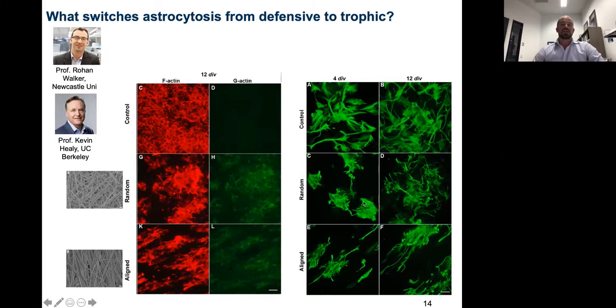What we found is that when we offered these three-dimensional architectures, these fibrous morphologies, which are electrospun polylactic acid fibers, the same as the degradable stitches you might get from a dentist that you don't have to remove, there's a much lower cytoplasmic volume, and these cells have a very different morphology to the inflamed ones up here. So we managed to maintain them in vitro, for the first time, in a state that was not inflammatory, like healthy astrocytes would be in your brain.